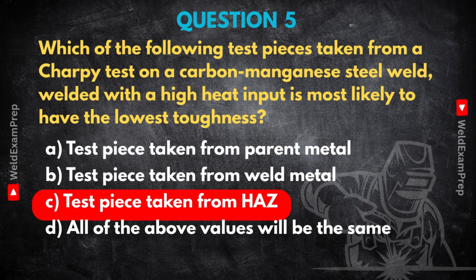What does that mean when an inspector looks at a WPS, and how does it affect thinking about the structure long term? It means an inspector needs to look really closely at the heat input limits specified in the WPS, particularly for materials like CMn steels. If the procedure allows for really high heat input, or if they see evidence that a welder has exceeded it, maybe wide weld beads, slow travel speed, red flags should go up. They should anticipate a potential drop in HAZ toughness. Maybe they'd recommend extra testing, like more Charpy tests focusing on the HAZ.